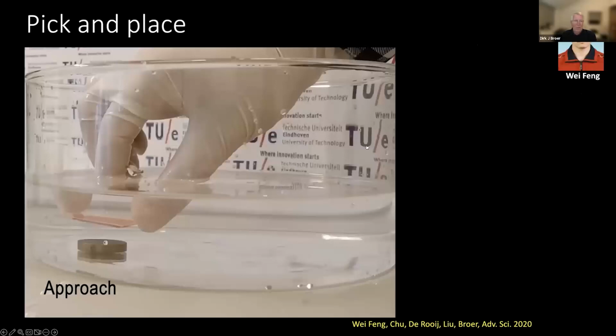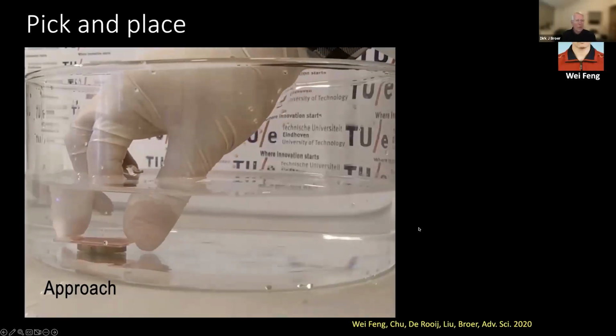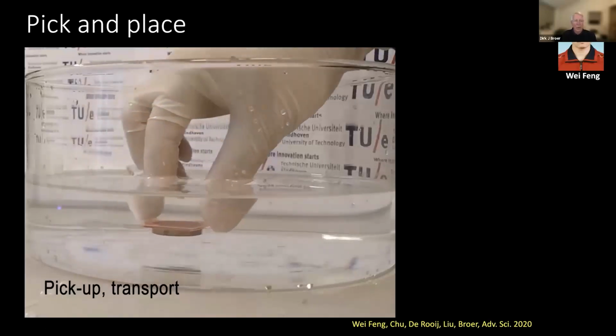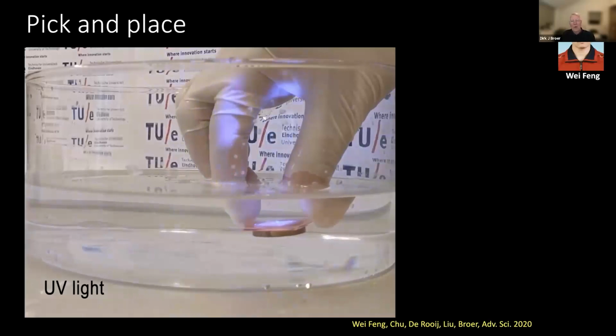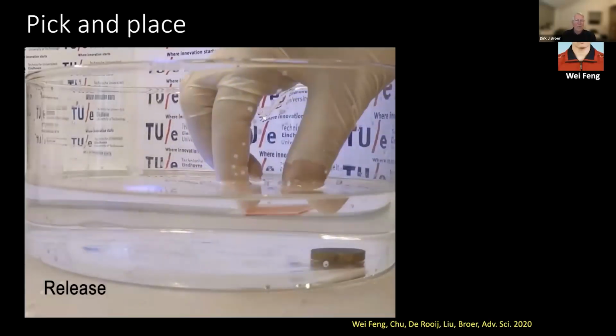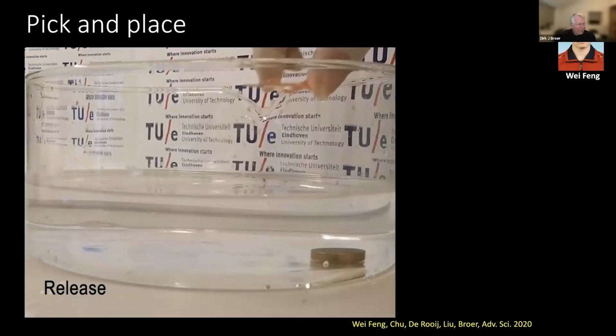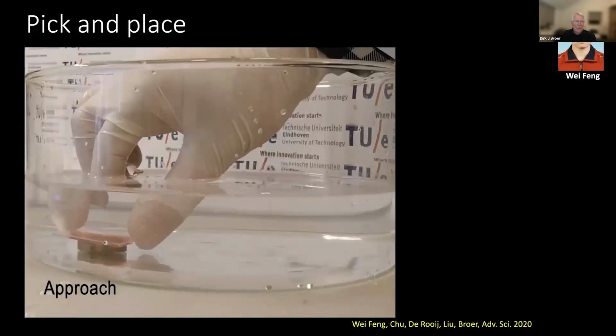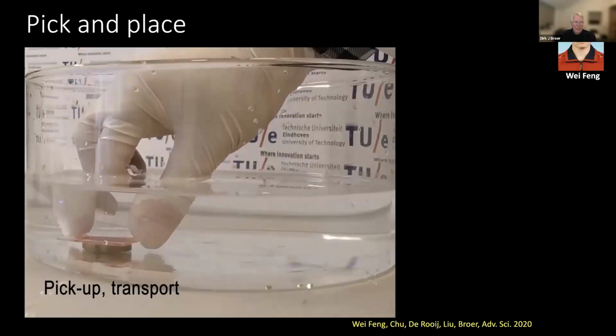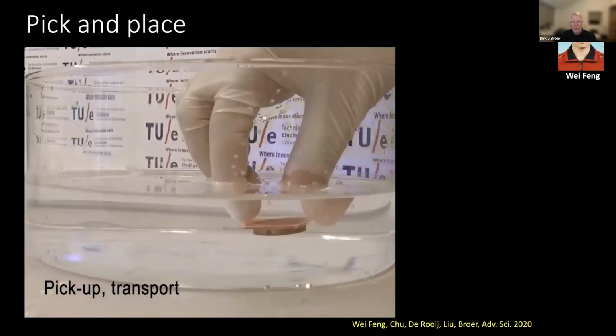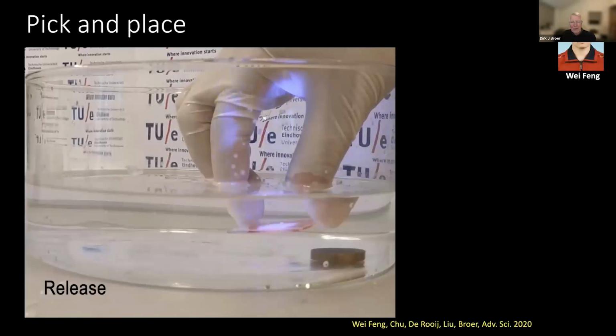And if you want to look for an application, then you can use it, for instance, as a pick and place machine. So here we have a copper block. Here we have the sample, and here we have the fingers from Wei Feng. And Wei Feng is now pressing the coating with the adhesive part to the copper block, then brings it to another place, exposes it with blue light, and then with UV light, and then it is released again. So that is another application that we could bring in place. Just to show once again, because I like the movie so much, released by UV light.